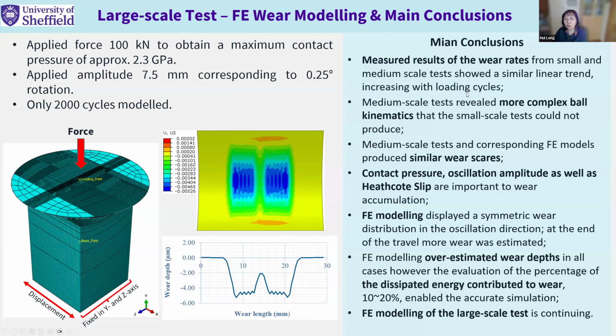Some main conclusions: the measured wear rate shows a similar linear trend, so basically it increases with load cycles. The medium scale test reveals more complex ball movement than the small scale, which couldn't produce it. FEA modeling and the test from the medium scale show similar wear patterns, and that also confirmed contact pressure, oscillation amplitude, and the Heathcote slip are important to wear accumulation.